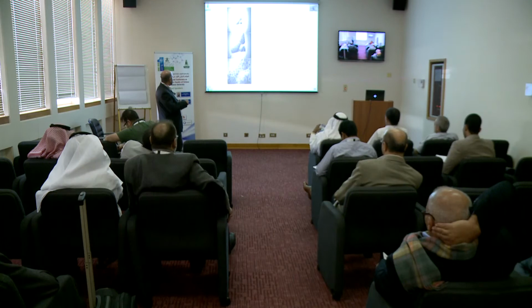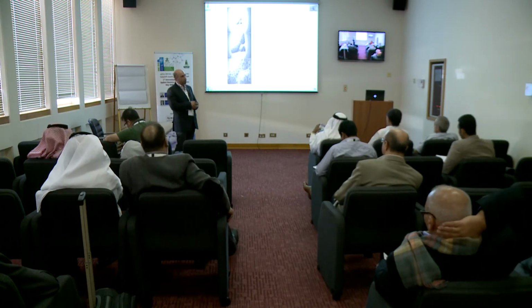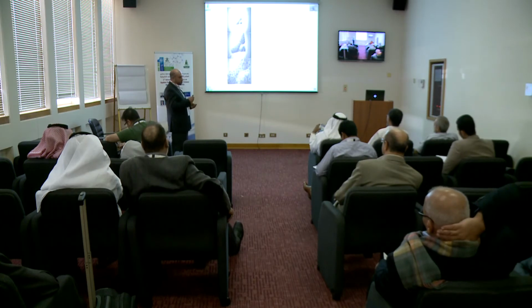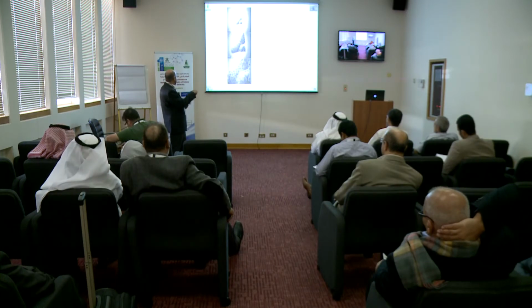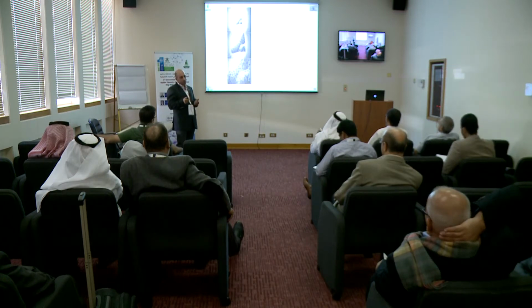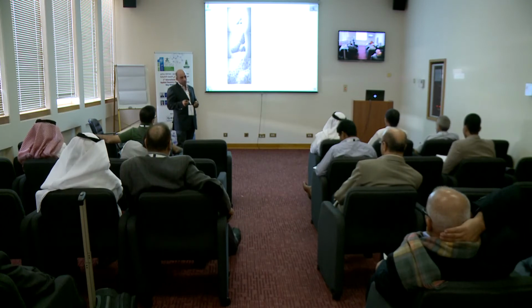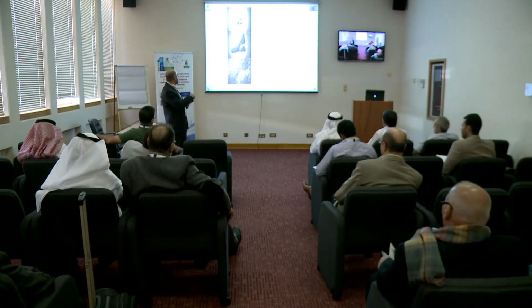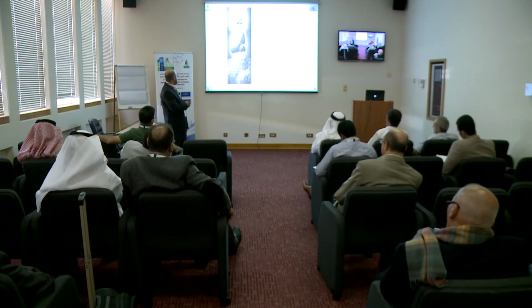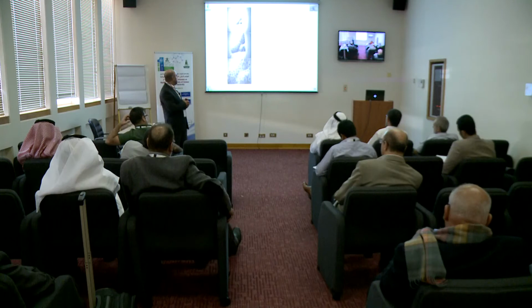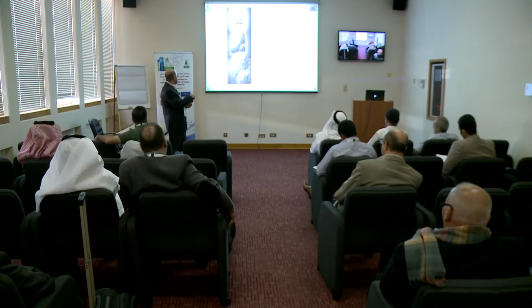This is the transmission electron microscope image of the iron nanoparticles supported on the nanographene. I'm just presenting a few things about that. As you can see, the graphene nanosheets exist as a plate, and the iron is homogeneously distributed over the graphene. One of the problems, again, of the iron nanoparticles, not just the chemical stability, not just oxidizing to iron oxide, but they are also magnetic materials. So once you add them to water or a solution, they agglomerate together, and that decreases their activity. So when we support them on a carbon-based surface like that, they don't agglomerate, they are distributed homogeneously around the surface like that.